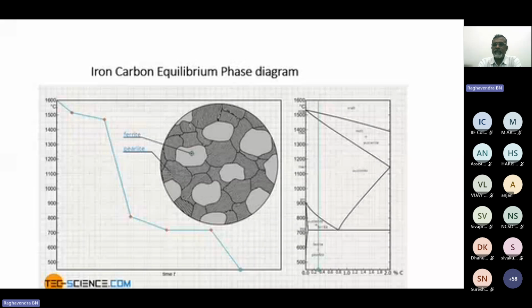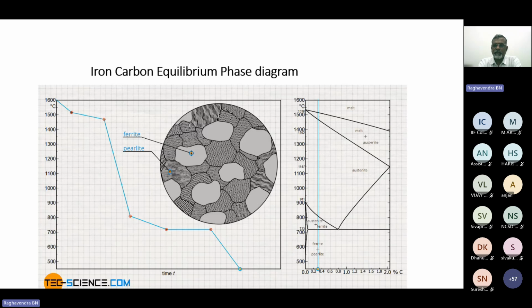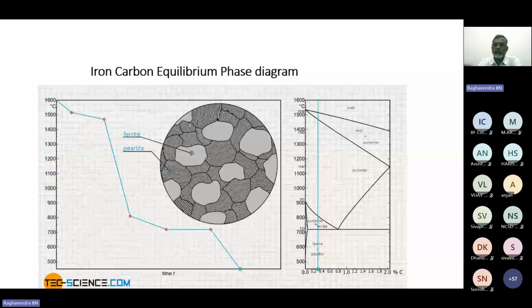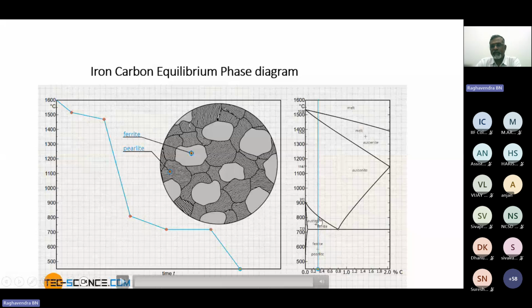Basically, this is around 0.3% carbon we have seen. This is how the transformation takes place at equilibrium. Equilibrium is very slow. Now if you want to heat it from room temperature to the melting point, the same process will repeat. If we are slowly heating it, the ferrite and pearlite above 723 will transform to austenite and ferrite, and when it crosses about 830, 840, again it will convert to austenite. Then it becomes austenite and liquid, then completely liquid. This is how the phase transformation takes place.